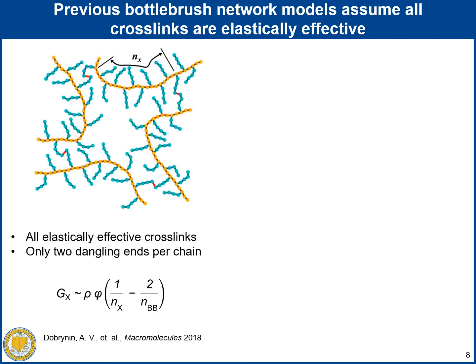However, additional network modeling is needed to not only control, but to predict the moduli from the Bottlebrush network structure. Here, let me first briefly summarize the previous approaches in the literature. One approach assumes that all crosslinks are elastically effective, meaning that all crosslinks are stress-bearing and linking the nearby polymers together. This assumption essentially treats the elastically ineffective crosslinks as the only two dangling ends per chain.